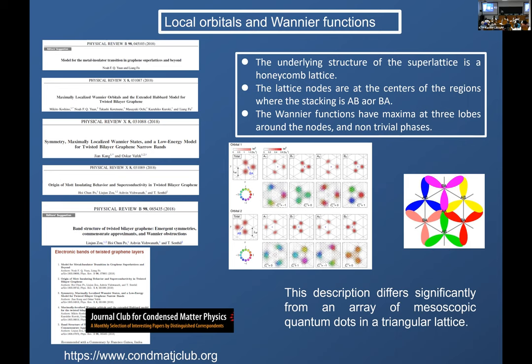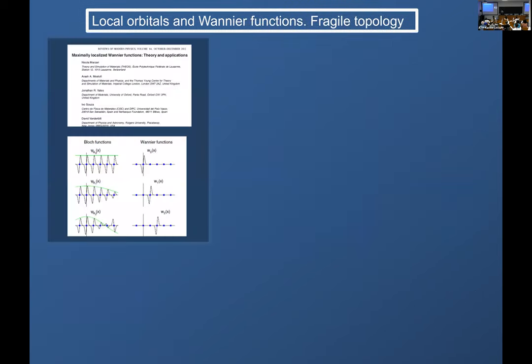Moreover, at the end of the day you can calculate them, for instance using tight binding calculations. As I mentioned, you get the Wannier functions which are very unusual. They have this fidget spinner shape, as they are called. They are defined in an effective honeycomb lattice of the size of the moiré unit cell. But they peak not at their origins but at the center of the unit cell. And they seem to overlap. Wannier functions by construction cannot overlap, but they are defined in different sublattice space. Again, that's uncommon. That's not the typical Wannier function you get in other flat bands, which you can characterize very easily in terms of atomic orbitals.